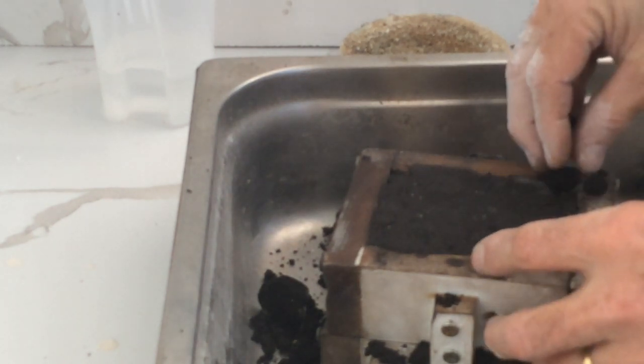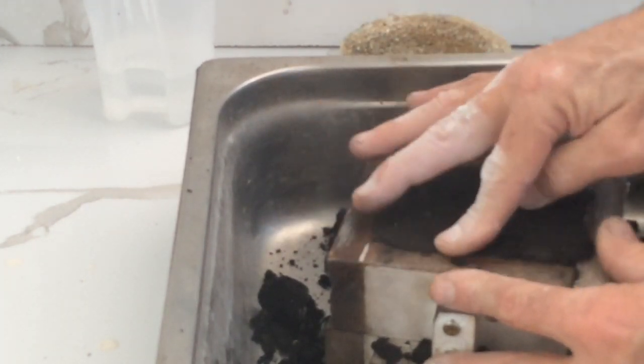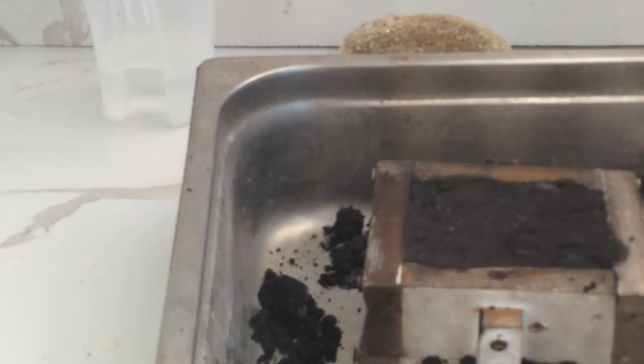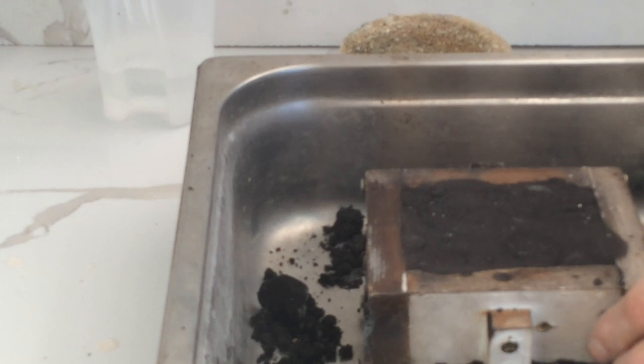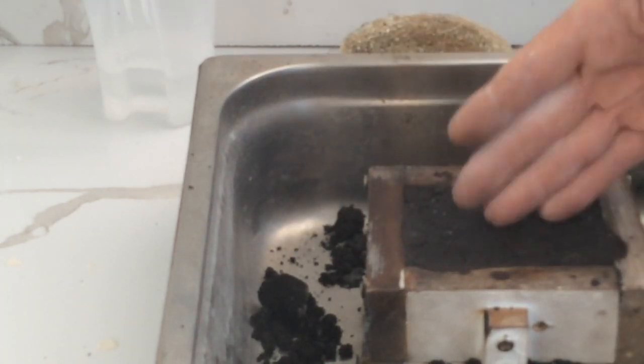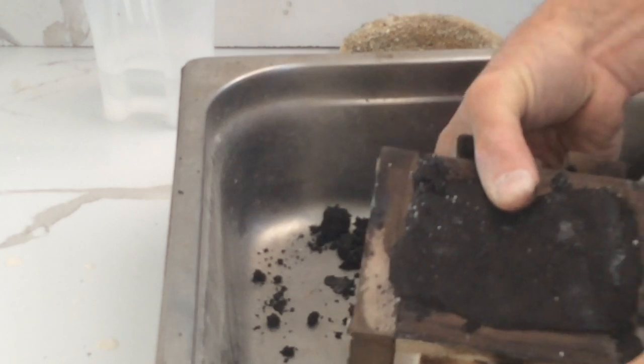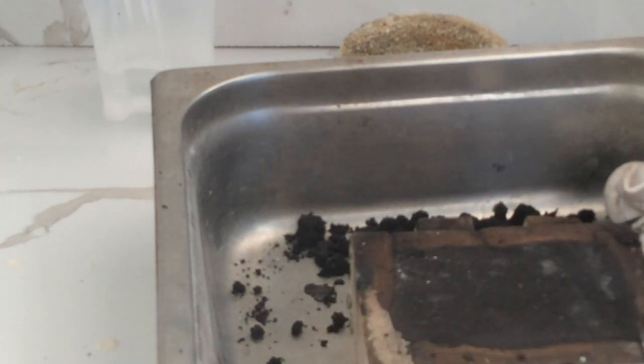I want to talk to you too. One of my friends in the comments has left me a message reminding me about how dangerous molten metal is. Now, my sand is a little bit porous, so it gives room for gases to escape. But when it comes to green sand and Delft clay and those ones that you buy, sometimes they're not quite as porous as you'd like. And if you don't put your own vents and things like that in it, there's a chance that when you pour the metal into it, it'll spew back out like a volcano and it can be extremely dangerous.